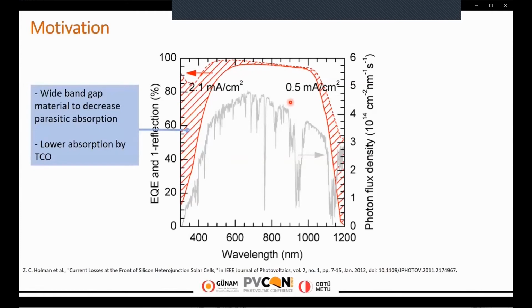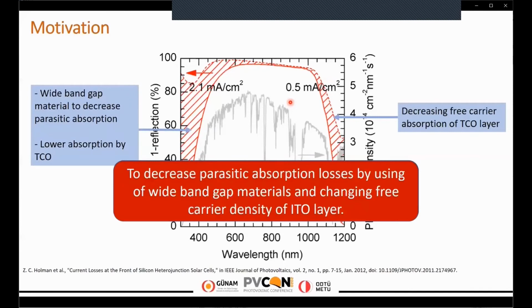Here, for the front side losses of the solar cell, it's possible to use wide bandgap material to decrease parasitic absorption, and also a TCO layer with a lower absorption coefficient can be used. On the rear side, the main loss mechanism belongs to free carrier absorption coming from the TCO layer. The main motivation of the study is to decrease parasitic absorption losses by two approaches. The first one is the integration of wide bandgap materials on the front side of the solar cell. The second one is changing the free carrier density of the ITO layer.